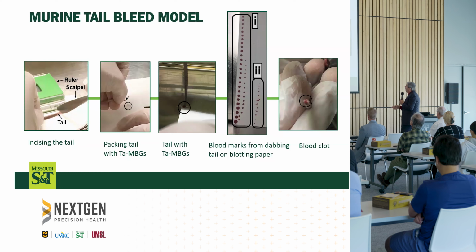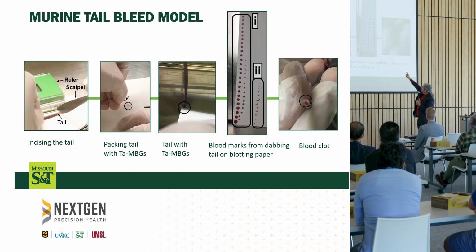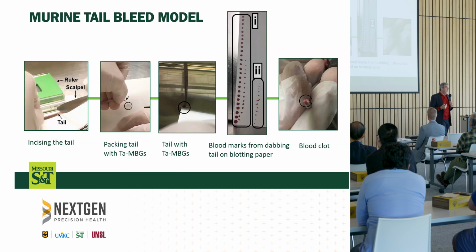And what you'll see from that, on number 2 here, is that the bleeding stops at a much quicker rate. So the bleeding time is dramatically reduced by the presence of our hemostat. There's a lot of artistic interpretations of this, as you can imagine, but this is the conventional way in which we evaluate these materials. The way to make it less open to interpretation is to have a standard, a commercial hemostat comparing to our material.